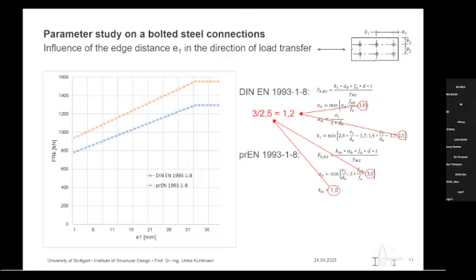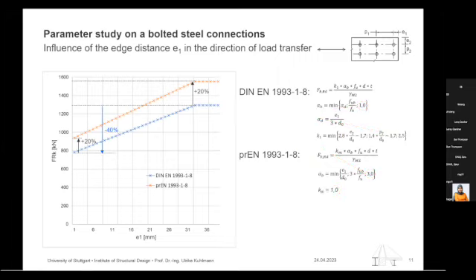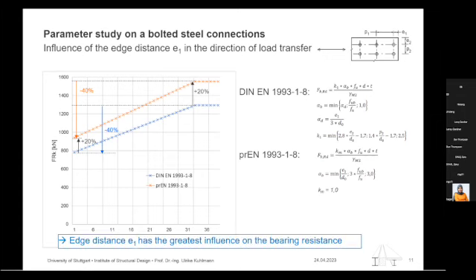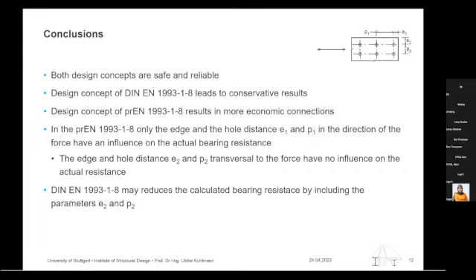This ratio value can also be seen in the calculated bearing resistance, because the results of the prEN 1993 are always 20% larger than those of the DIN EN. However, it can also be seen that only by changing the edge distance e1, the bearing resistance of this whole connection can be reduced by up to 40% for both designs. In the end, the parameter study has shown that the edge distance e1 has the greatest influence on the bearing resistance. And yeah, to come to my conclusion,